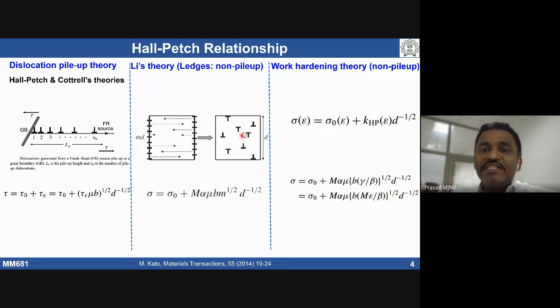Resistance is going to be offered by these forest dislocations. So the density of forest dislocations is considered to derive how the stress is going to depend on the grain size of a material. The number of ledges and dislocation density are related, and one can arrive at this equation by using ledge theory.